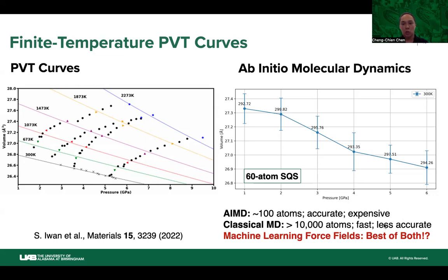Okay, so now the trend is to consider the so-called machine learning force fields. One of the most popular state-of-the-art research directions is able to obtain the best of both methods. So you will enable large-scale simulations using classical MD, but meanwhile with the potential and the corresponding parameters learned from ab initio molecular dynamics data. So this is one of the directions we are now pursuing.